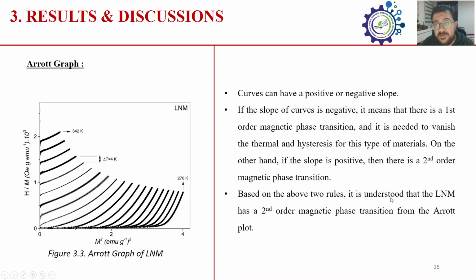Curves can have a positive or negative slope. If the slope of the curves is negative, it means that there is a first order magnetic phase transition, and thermal hysteresis needs to vanish for this type of material. On the other hand, if the slope is positive, then there is a second order magnetic phase transition. Based on the above two rules, it is understood that LNM has a second order magnetic phase transition from the Arrott plot.